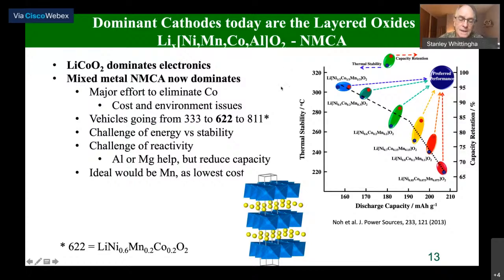Almost all today's batteries use these layered oxides, so this is exactly the same structure as TiS2. So metal oxide, octahedra joined together, lithium in between. In the real materials, there's some exchange because we have entropy involved. So there's 3 to 5% of lithium will be in this layer, and 3 to 5% of nickel will go into the lithium layer. A little bit is good because this stops the layer shifting relative to one another when you take the lithium out. The big challenge with these materials is the best material for energy density, which is high nickel, is unstable.